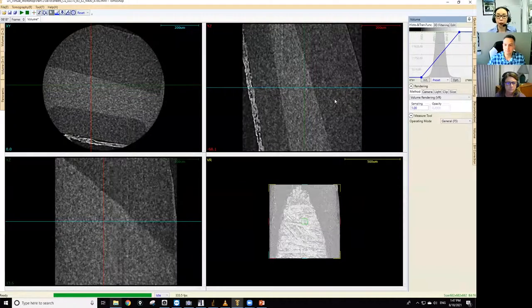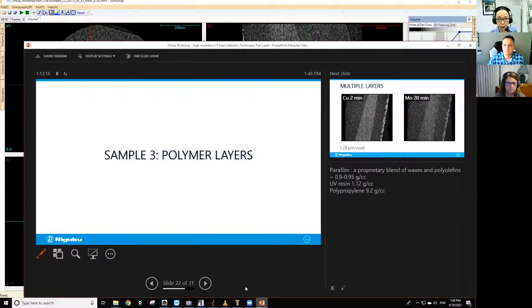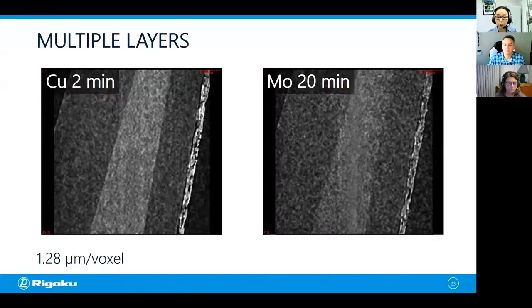So this is a scan by copper 8 kV radiation. And by the way, that is the right choice. But let's see what happens if you did the same scan with molybdenum radiation. So let me switch back. Okay. So this is the comparison. The scan on the left is the one we just did, copper radiation, 2-minute scan. The one on the right is the molybdenum scan, but we spent 20 minutes just to see some difference.